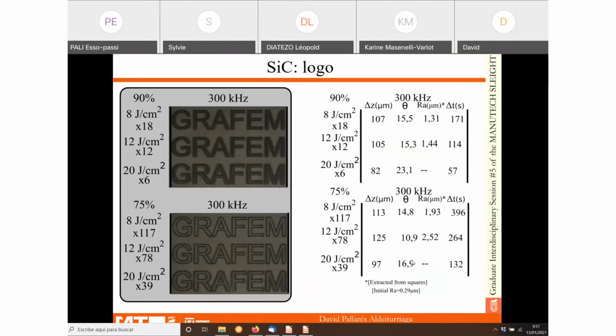Okay, and finally, silicon carbide. First thing that we see here is that it's a material particularly difficult to inscribe. Please take a look at 8 joules and 75%. It takes more than 100 scans, which makes the elapsed time 400, which is a lot of time compared to PEEK. And also, please take into account that we are using 300 kilohertz. So it's a material more difficult to engrave, but it's of course possible.